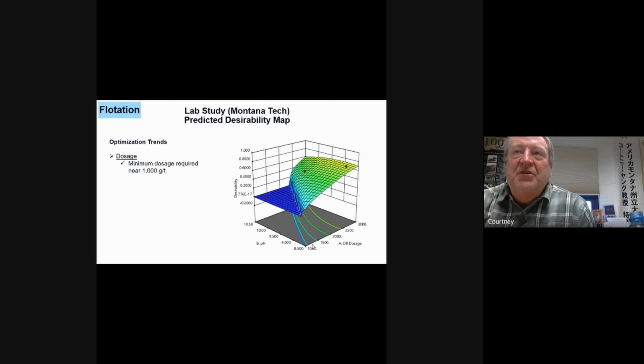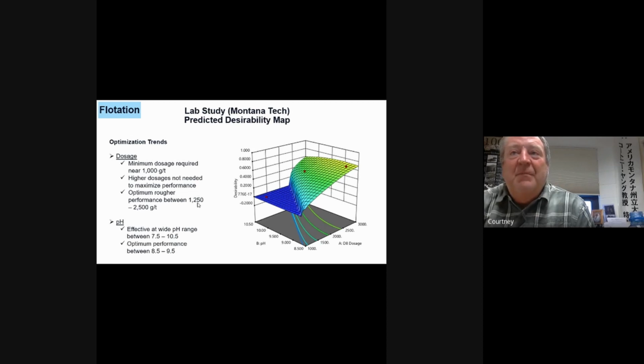So the minimum dosage required, at least greater than 1000. Again, 1200 is probably good. Higher dosages just are not needed to maximize performance. And I can say that because these are rougher floats, and we also have 3 cleaner stages after that. So anywhere between 1250 and 2500 works. 1250, 1200, give or take, that's about where you want to be. pH range 7.5 to 10.5, but the effective range is 8.5 to 9.5.